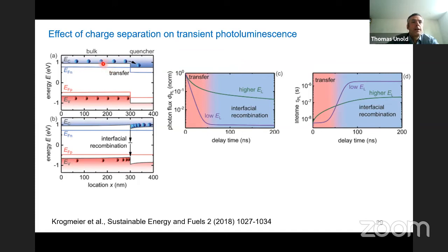And what's shown here is that if you do a transient experiment, then first you get this charge separation. So you get the electrons going into your contact or transport layer, and then they accumulate there, block further charge transfer into the layer, but then lead to a very strong interfacial recombination until you have some kind of a steady state reached. And if you look at the transients here, this is the PL transient shown over delay time, then this depends again very strongly on the excitation conditions.